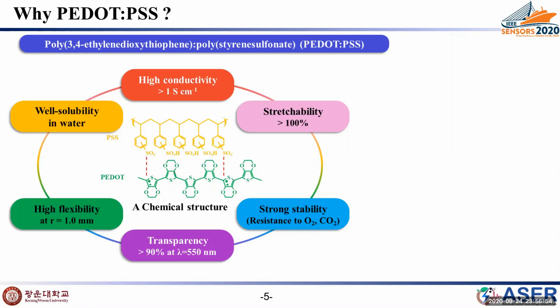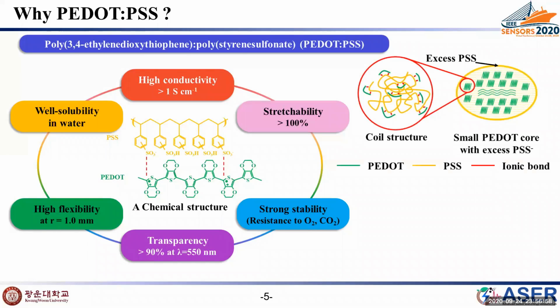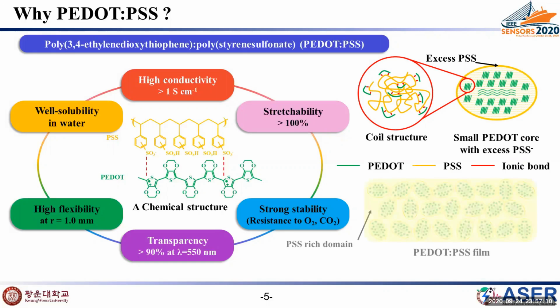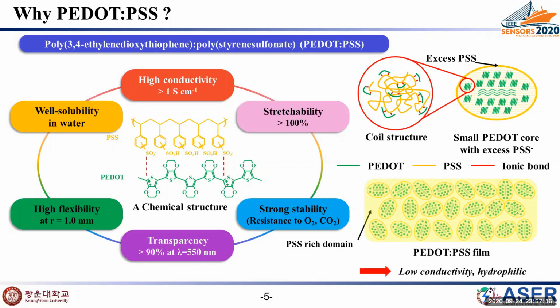However, despite these advantages, as you can see from its structure on the right side, the ionic bonds between the conductive PEDOT and the insulating PSS form a coil-like structure, resulting in a small grain size. So when PEDOT:PSS is formed into film, it has low conductivity and is very hydrophilic due to excess PSS